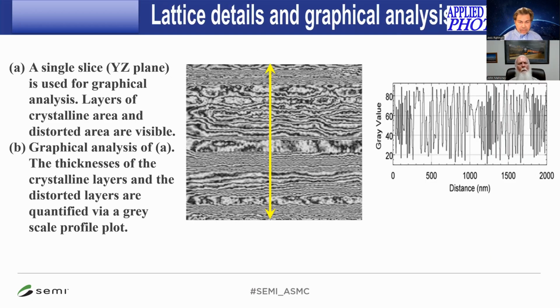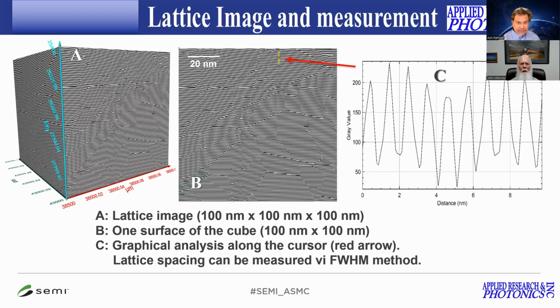If we take only one of the slices, we can see the details, the morphology across the thickness. Then we can do what we call a graphical analysis, and with it we can measure the thickness of each lattice plane that has distorted or remained good. So each can be quantified. The only other thing I'm going to show here is a lattice image of a different sample, whereby we can measure the lattice parameters as well.